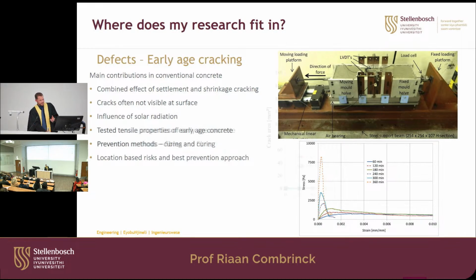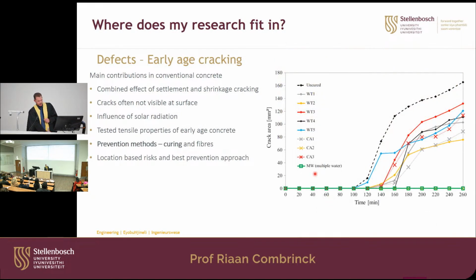Okay, then preventative measures. We looked a lot at curing and fibers. This is the crack area with time, and you can see this is uncured samples. Once you add a little bit of curing, this is normally curing water, you can see you reduce the cracking size, but with multiple curing methods and curing agents, you can even prevent the cracks completely.